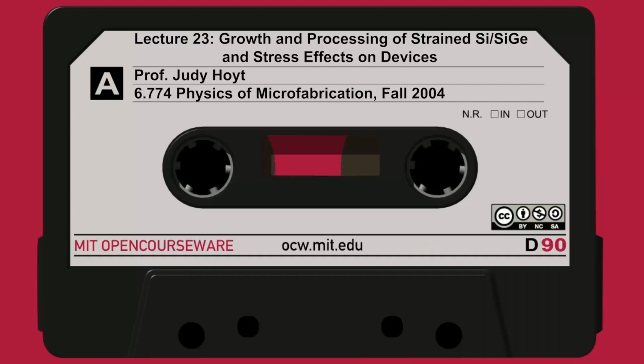It was gone. The red line is for the germanium that was annealed in an inert ambient. It diffused a little bit during this rapid thermal anneal, but you can ignore the surface peak because that's sort of a SIMS artifact. But at least it didn't go all the way. This is a very preliminary result and it has to be repeated, but it indicates that processes that inject vacancies probably should be avoided if you're trying to control the diffusion of germanium. There is a lot of interest in doing processes to inject interstitials, inject vacancies, all the same kind of process. The tests that have been done in silicon can now be done in strained silicon on silicon germanium to see how the germanium diffuses, or even how the dopants diffuse.